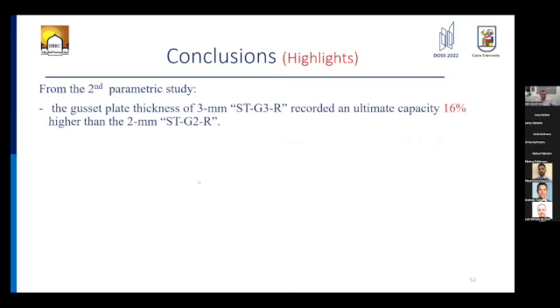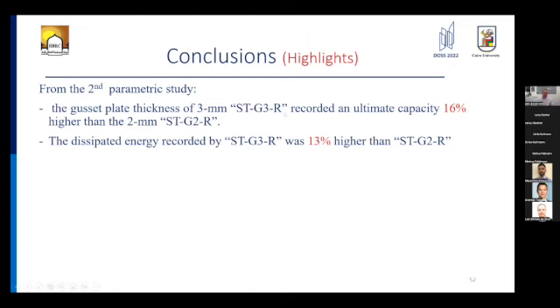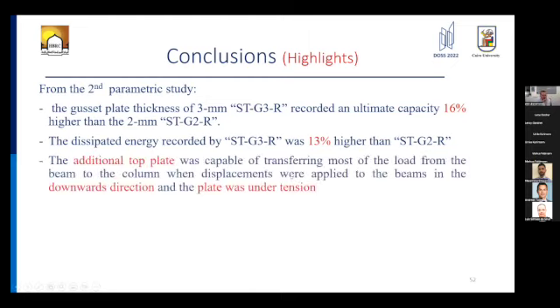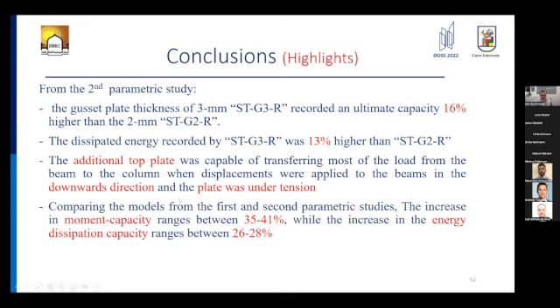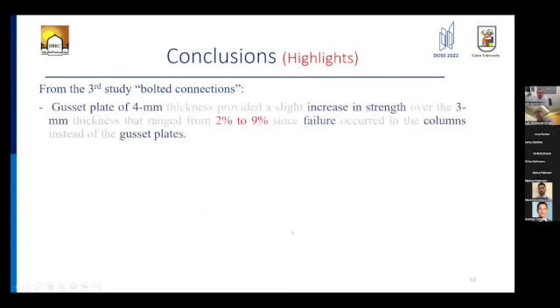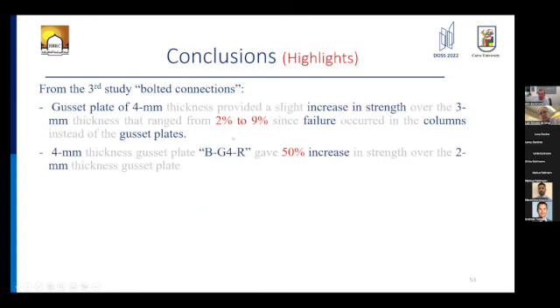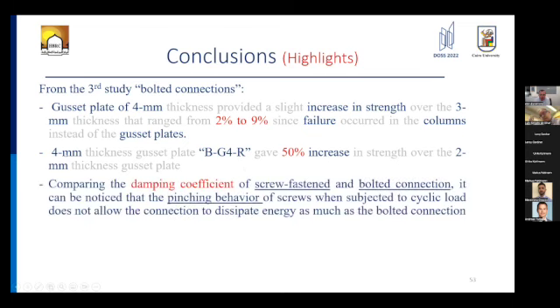From the second parametric study, a similar conclusion can be drawn. While changing the gusset plate thickness affected the capacity by 16% and dissipated energy by 13%, the additional top plate managed to increase the resistance of the connection significantly. This increase reached 41% in the moment capacity and 28% in the dissipated energy. The conclusion from the third and last parametric study is that the gusset plate thickness only increased the capacity by 9% in strength, while the 4 millimeter gusset plate thickness gave a 50% increase over the 2 millimeter.